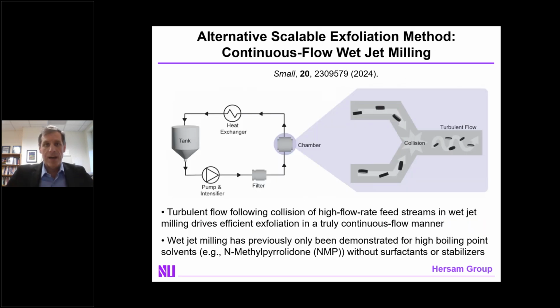And so what we've been doing in our lab more recently is exploring true continuous flow methodologies for agitating these solutions and achieving exfoliation. The one which is working best at the moment is wet jet milling. Wet jet milling takes your initial dispersion, splits it into two streams, which are then accelerated and collided together. The resulting turbulent flow then drives efficient exfoliation in a truly continuous flow manner. While this method has been demonstrated previously, in this context, it's always been done using high boiling point solvents like N-methylpyrrolidone. This leads to some significant challenges from an environmental or sustainability perspective.